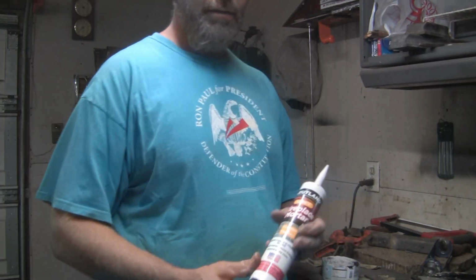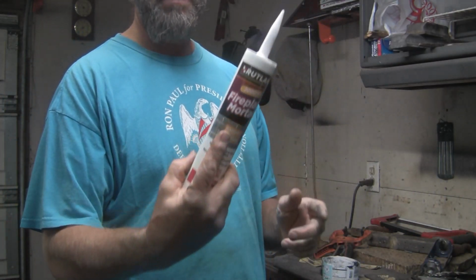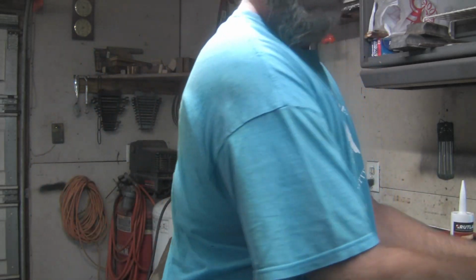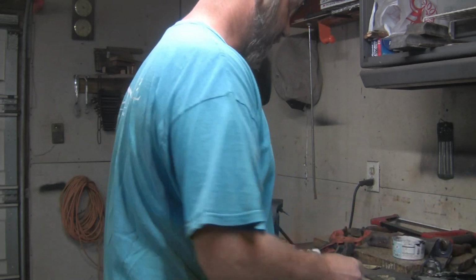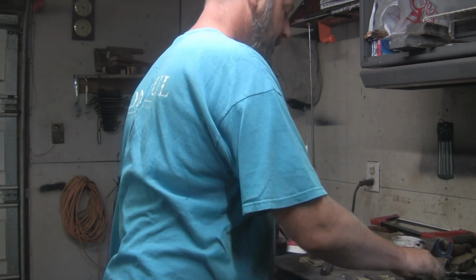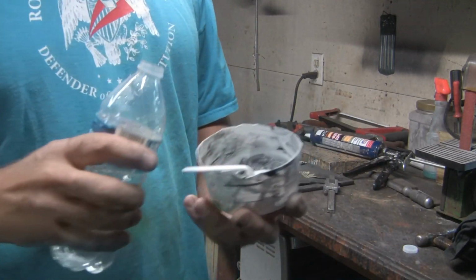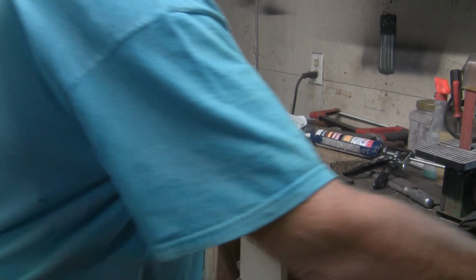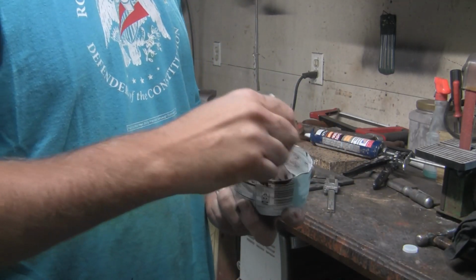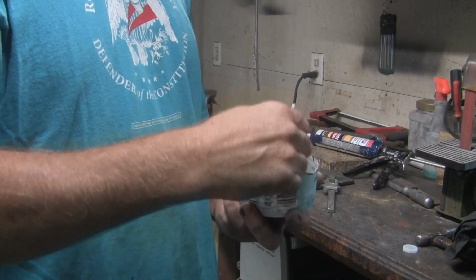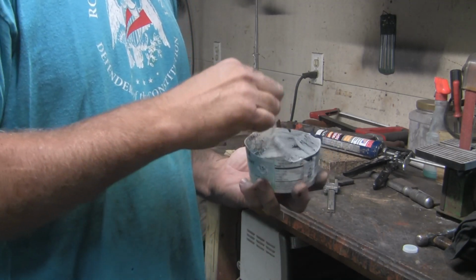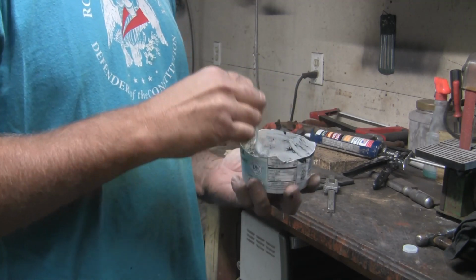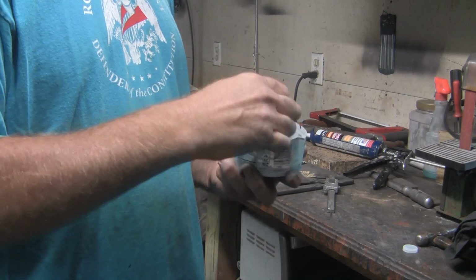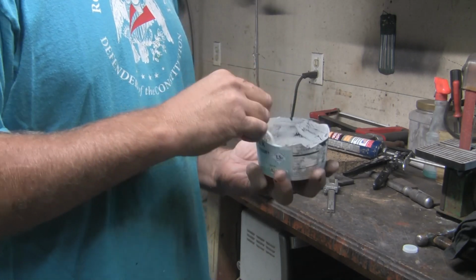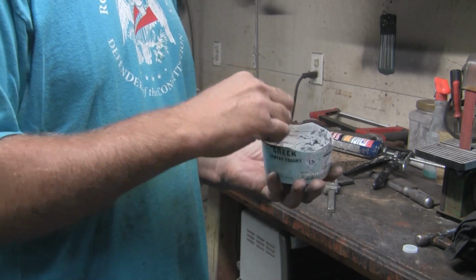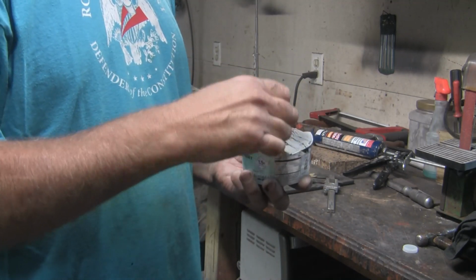All right, so a little bit of a correction. I had the wrong tube. I'm going to use this fireplace mortar. That's good up to 2,000 degrees. I grabbed the wrong tube out of the cabinet. All right, so this is going to be a really thin coat, so I want to make this kind of watery. And I'll add water or add mortar as I go until I get it to the consistency I want. This is almost like a primer, I guess. A thin coat to help get everything to stick, versus just smearing on a really thick coat.